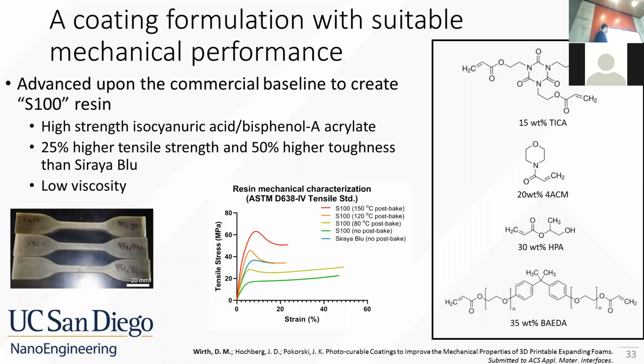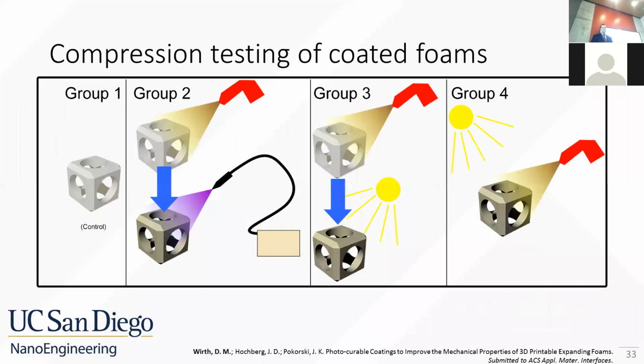So if you want a high toughness resin, you can post bake between 80 and 120 C. If you want a high strength resin at the expense of a bit of brittleness, you can post bake between 120 and 150. Next step was to do a bit more rigorous testing on the full-up foam composites using these 1-inch sample cubes created out of foam.